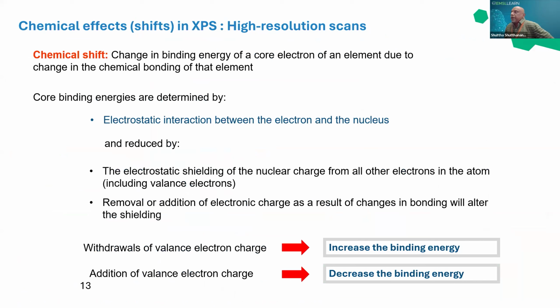So the main thing about XPS is the chemical shift. What is the chemical shift? It is basically a change in the binding energy of the core electron because of the changing chemical environment. For example, if you take aluminum in a metal, aluminum will have nearest neighbors that are aluminum, but if you take aluminum oxide, it will have oxygen as nearest neighbors. Because of this changing environment, the binding energy of that particular aluminum 2p electron is going to change. That's what we are going to measure in this chemical shift in the XPS.